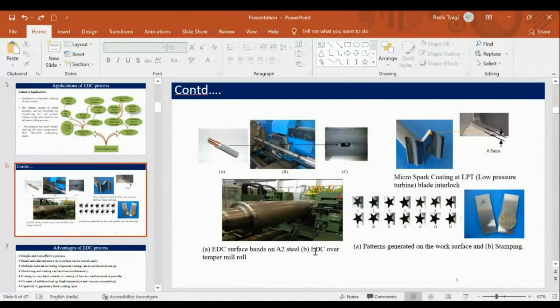Also, EDC is used on the temper mill roll, which is used for the production of steel sheet. The texturing is done there. Also, as I have told you, EDC is used on turbine blades. This is the turbine blade that you can see in this image. This is a thick coating of 0.5 mm that is deposited on the turbine blade to repair it when it deteriorates during the process.